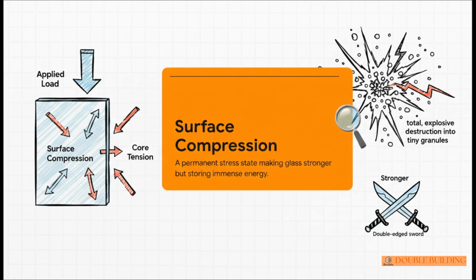Any applied load has to overcome that massive surface compression before the glass fails. This incredible engineering is exactly what makes tempered glass 4 to 5 times stronger than standard annealed glass. But it is a double-edged sword. That immense stored elastic energy guarantees total explosive destruction into tiny granules when it finally yields.